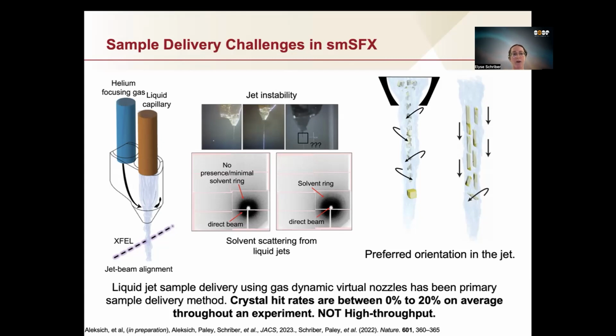And I heard a great quote from a paper that I was reading, that there should not ever be any thinking done at an XFEL experiment because we can't think fast enough. And that's true. An XFEL is so much faster than us, and every single problem that arises, we're seeing it far too late. The other problem we run into is that some crystals, especially needle-shaped crystals, tend to actually preferentially orient as a result of the forces that the jet itself is placing upon them. And what that means is that we have to then sample more and more of that particular crystal because we get only a specific orientation.